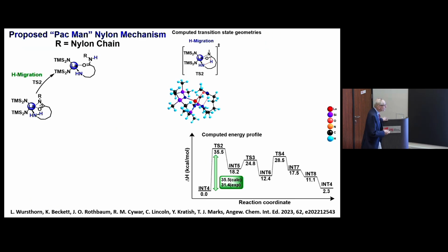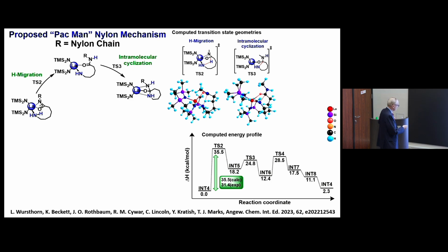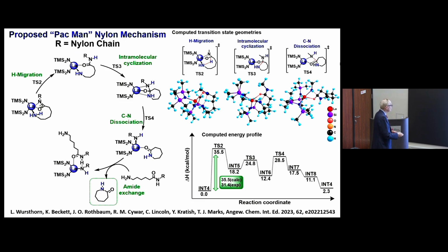So here's the mechanism. And the first step then is coordination of the end. We call it the Pac-Man mechanism. It just chomps away on the nylon chain, and when it gets to the end, it jumps to another chain. So the first step then is forming this kind of structure. And then there's an intramolecular nucleophilic attack of this amino group, it's actually an amide, to the carbon of the carbonyl group. And then the next step is it dissociates and caprolactam comes out, and then another chain starts.